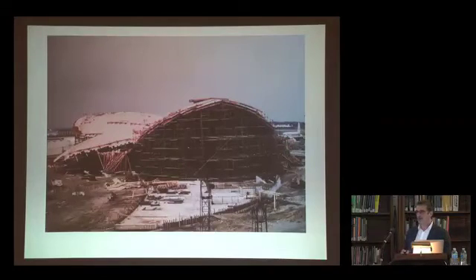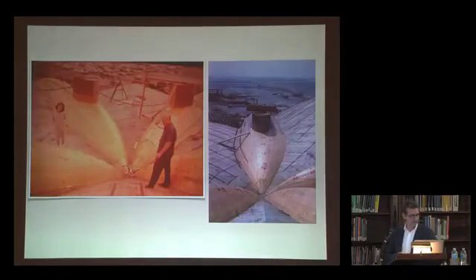Basically, the level of craftsmanship here was absolutely essential, because if there was a mistake here, the mistake would show in the concrete, and if the mistake showed in the concrete, the lines that Saarinen were looking for would not be there. And just one little anecdote, the engineer wanted to create the peaks as they were curved, and he was absolutely dead set against that. He said, when I fly in on an airplane, I want to be able to look down and see an edge there. So, we're talking about levels of detail that are very well understood and focused.